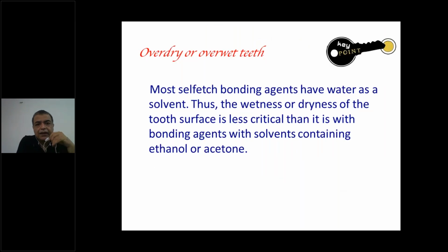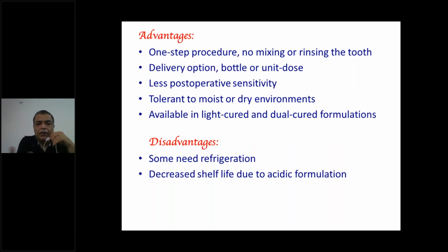So how do we tackle that? Most of the newer bonding agents, which are self-etch, are water-based and not based on ethanol or acetone. So this single-step self-etch bonding agent gives us a lot of advantages, where you have no mixing or rinsing of the tooth, so you don't have to dry it. And it gives you less post-operative sensitivity, because it is not removing the smear layer, but penetrating the smear layer and incorporating it in the hybrid layer. So the dentine tubules are blocked, and this works in moist and dry environments, and you can have light cure or dual cure. The only disadvantage is it has to be refrigerated, and the shelf life is a little lesser.